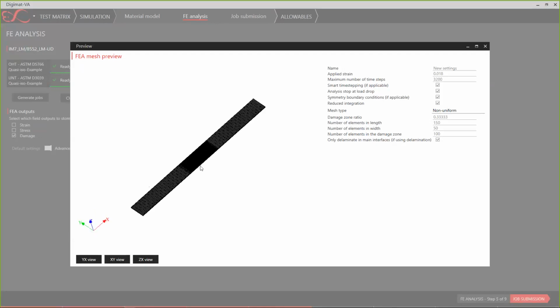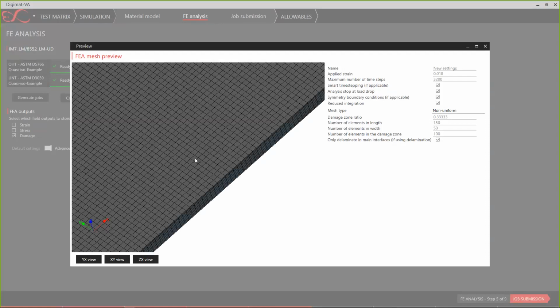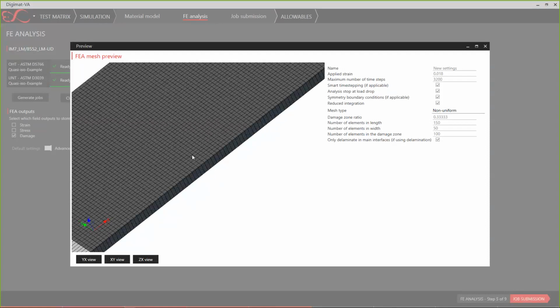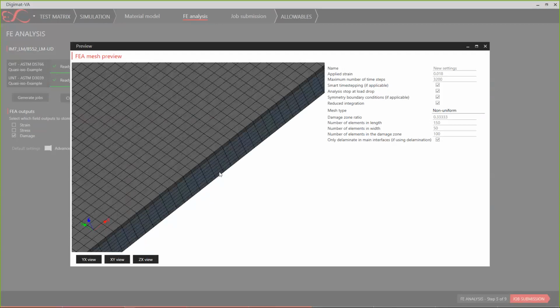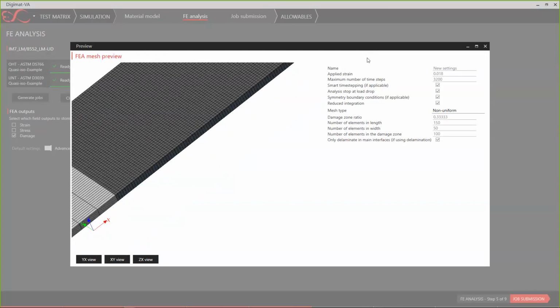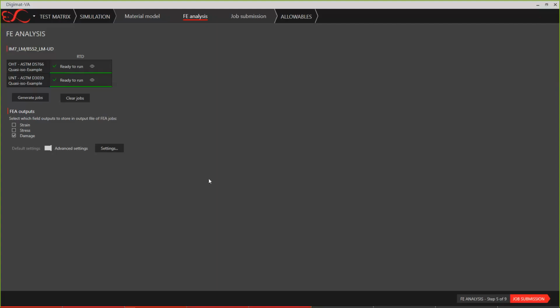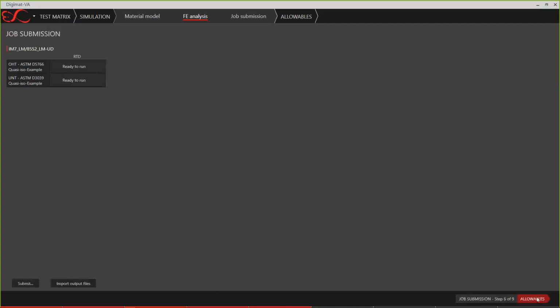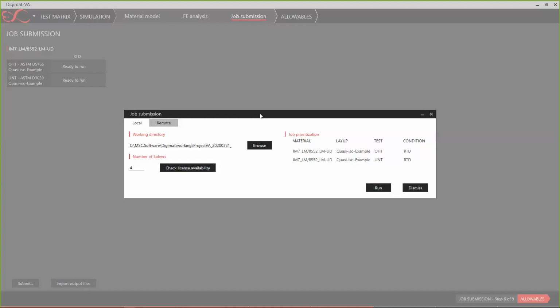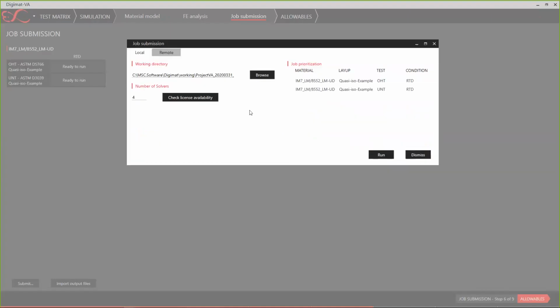Again, if we zoom, we have a specific size to make sure that we are going to reproduce properly the failure. And we have also different colors. Again, this is due to the in situ strength and the position of the ply within the thickness of the laminate, if we are at the symmetry plane, if we are external, or if we are inside the laminate. Once we have done this, then we are in the situation that we can execute the test matrix.